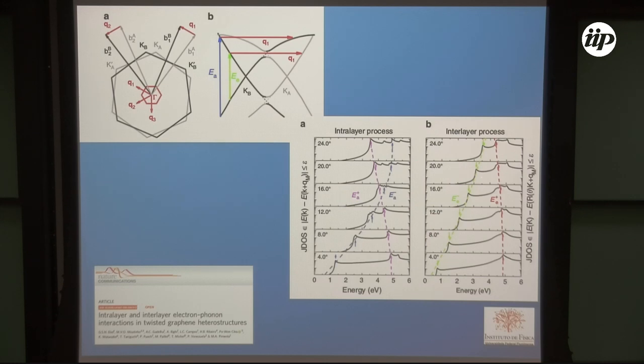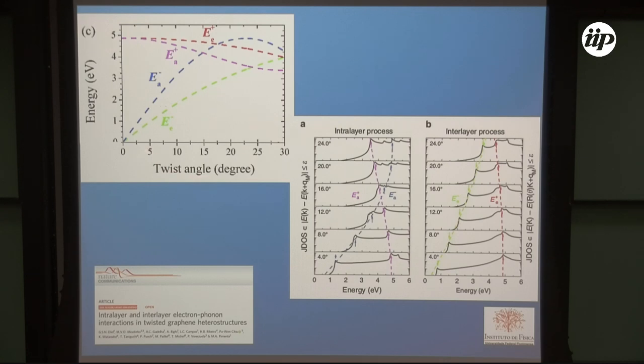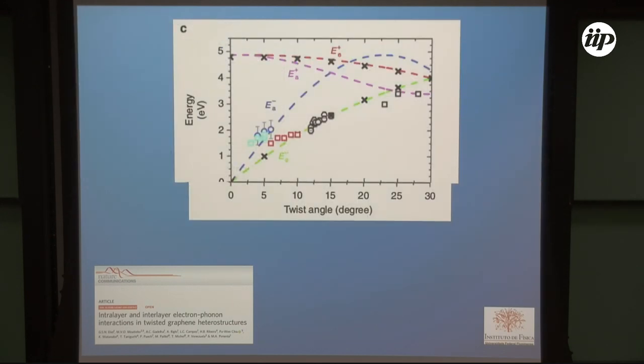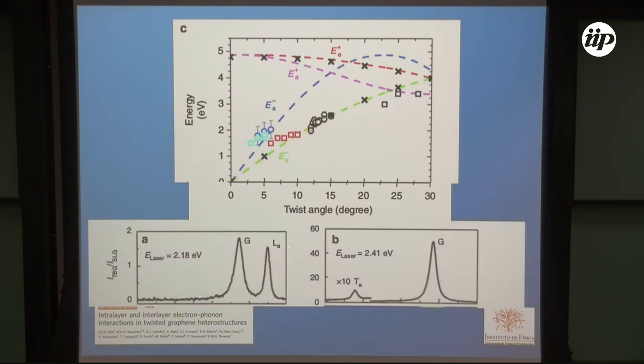Now we can put these two curves in a map like that. So here I have these energies as a function of angle, okay? And when I put the experimental data, they fit very nicely. So now we can say the origin of these peaks, concerning not only whether they come from longitudinal or transverse phonons, but also whether they come from intralayer or interlayer processes. So we are proposing another nomenclature. The peak can be L or T, and also can be A or E. So you can have also LE and TA.